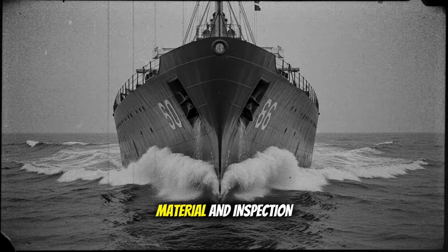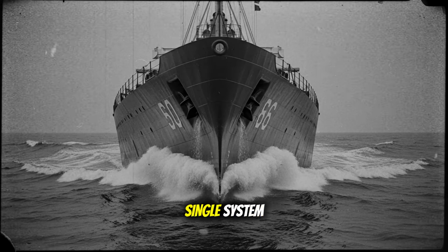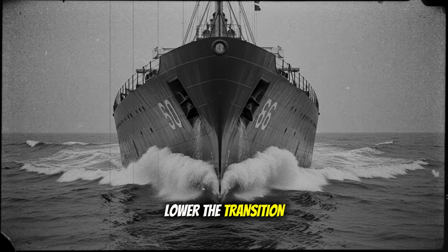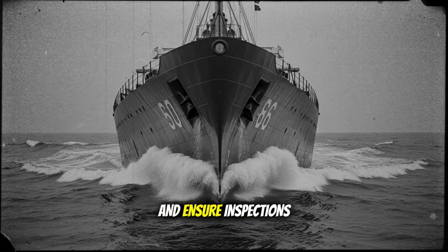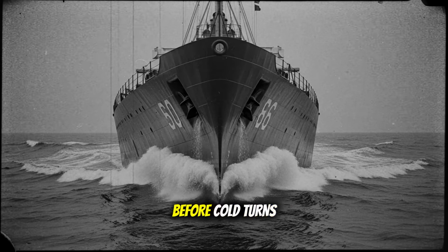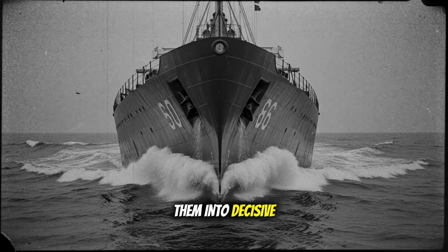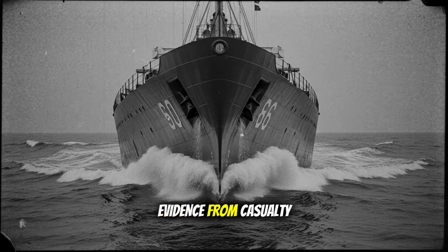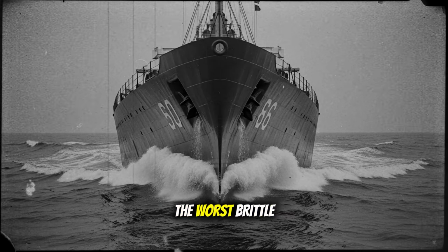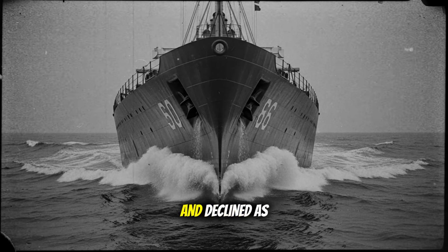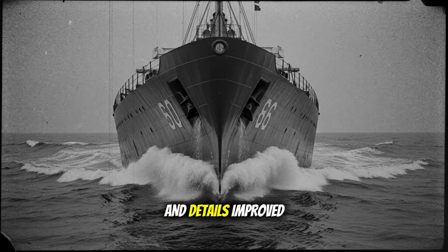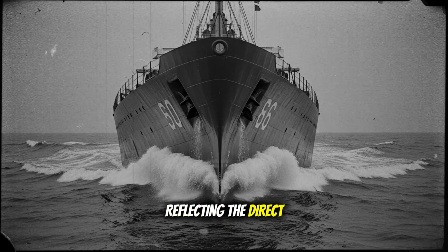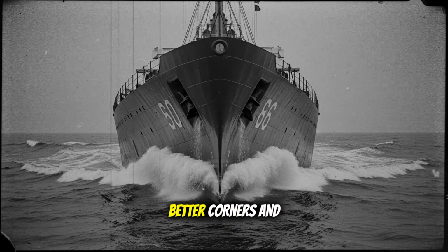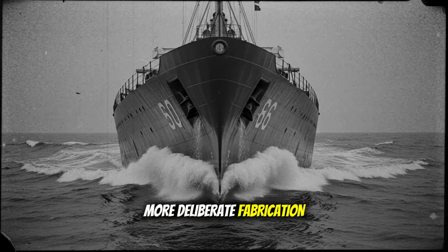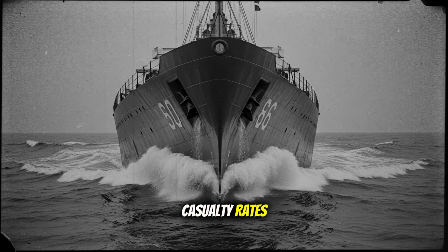Design, material, and inspection thus became a single system: lower the transition, blunt the notch, and ensure inspections find small flaws before cold turns them into decisive ones. Evidence from casualty patterns confirmed that the worst brittle fractures clustered in winter and declined as post-war steels and details improved, reflecting the direct impact of tougher plate, better corners, and more deliberate fabrication on real-world casualty rates.